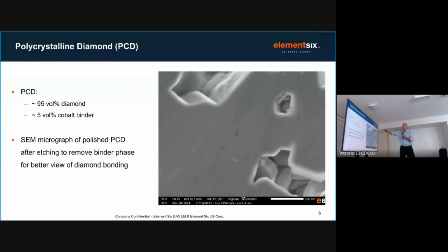I've now etched away the binder to make it easier to see. So in your mind's eye, you can imagine, well, if that's a grain boundary between the diamond grains, then what we're going to try and do is have a crack deflecting at the grain boundaries. And also, once it goes into the binder pool, this nice soft, squidgy cobalt pool absorbs the crack energy. So that's the toughening of polycrystalline diamond.